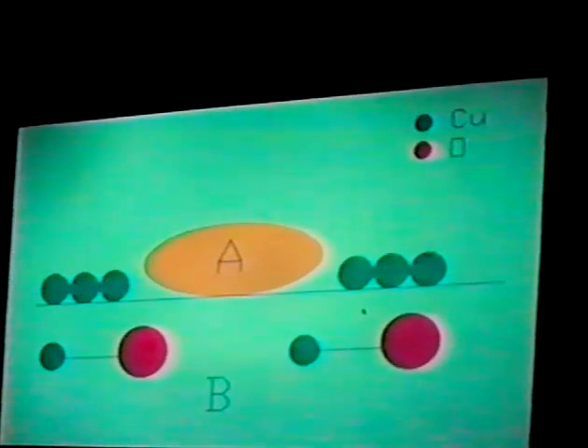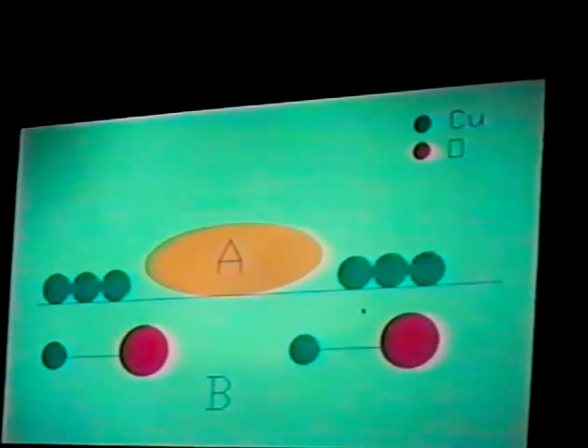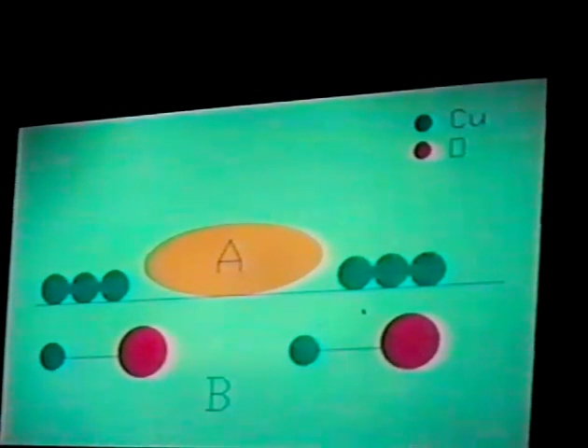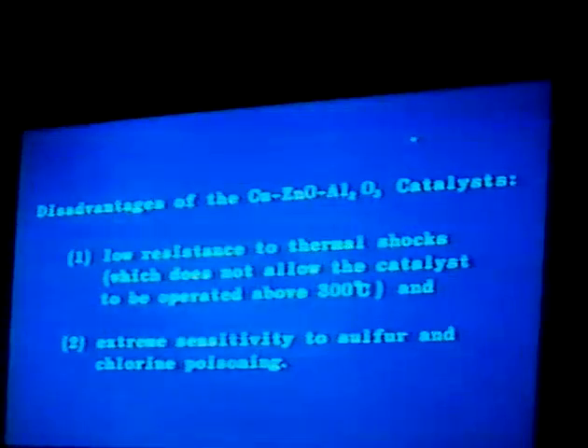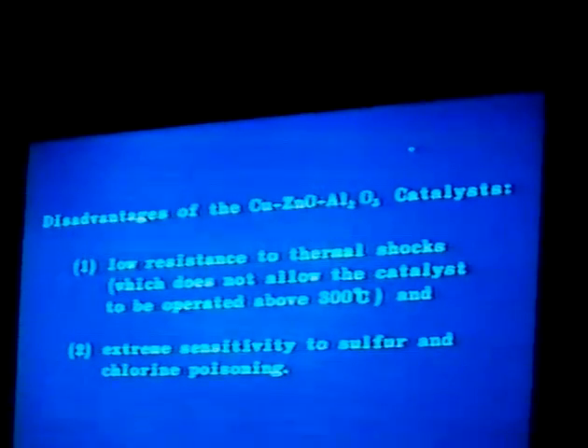distribution is there. The green one is some neutral copper species located on the surface. They are EPR silent. So now we can convince ourselves copper has something. But what about what we originally suggested, the copper, zinc oxide, aluminum oxide catalyst? It has a big disadvantage. Mainly it's the low resistance to thermal shocks, which does not allow the catalyst to be operated above 300 degrees centigrade, according to the report from SRI.